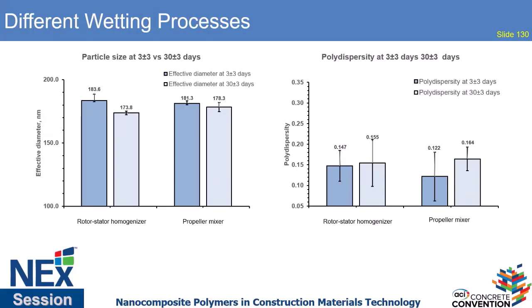So we were also using different wetting processes or different techniques. We started with a rotor stator homogenizer, and this method was not a problem if you're just dispersing the titanium dioxide nanoparticles. It became a huge problem when we were working with the surfactants. The anionic surfactants foam, so when you're using very high shearing, you create a lot of foam. It's a very stable foam, and it's something that is not wanted, especially in coatings.